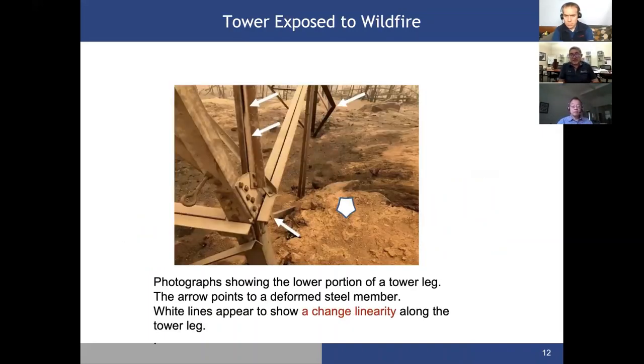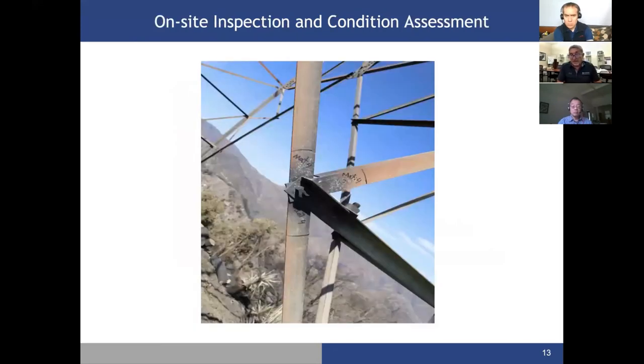Let's look at some examples. This photograph is showing a tower leg, and the arrows point to deformed steel. And basically, you can clearly see a change in linearity along the tower leg. The next one is the condition assessment after exposure to fire. What you like to do is non-destructive testing at different areas of the tower that especially exhibit discoloration. You can clearly see discoloration. It doesn't look like dull looking galvanized steel. It looks like it's staining. It looks like there are dark colors. So those areas are important and should be assessed by non-destructive testing as indirect measurement in the beginning.